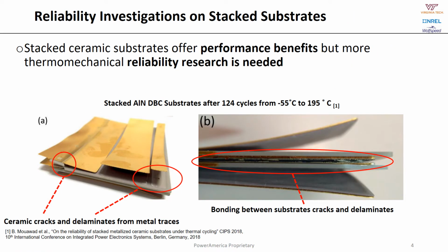In order to fully harness all of the benefits of stacked substrates, we need to ensure that the reliability of those substrate stacks is equivalent or greater than the reliability of the rest of the components in our package. There's little research currently done on the reliability, particularly the thermomechanical reliability of stacked substrates, and the research that currently exists does not examine the large area silver sintering that we use to bond our substrates at CPES, which I'll discuss in a later slide.